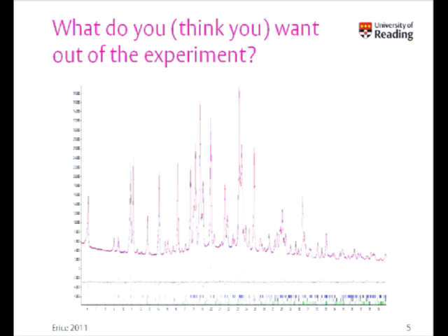But at the end of the 3-week period, when we solved the structure for them, we found that present in the sample, the blue tick marks correspond to the co-crystal, the black and the green tick marks actually correspond to starting materials. So once we're aware of that, we can index, we can extract, we can solve, we can refine, all straightforward.